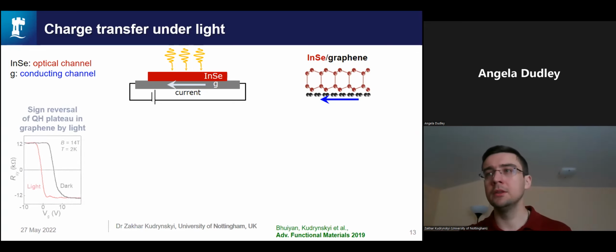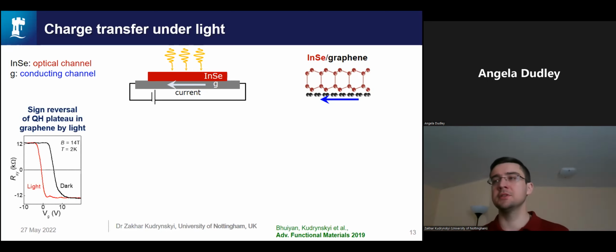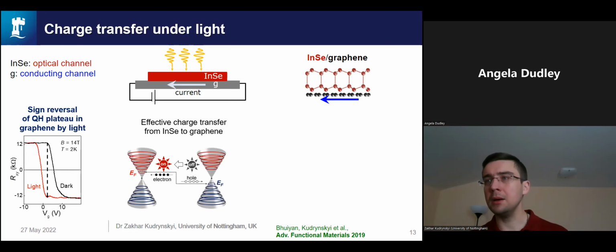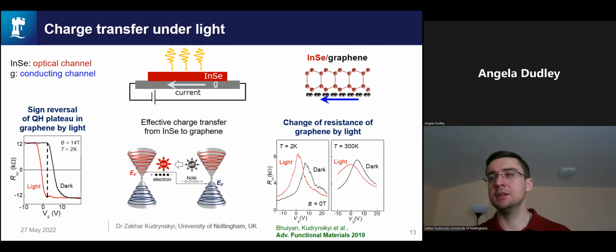So we can look at the Hall resistance versus gate, but also in the dark and under illumination. And you can see that under light illumination, we can change the sign of the Hall resistance. By light illumination, we can effectively change the electron density in the graphene, going from hole type of conductivity to electron type of conductivity. So this also changes the resistance. We can see that the change in resistance under light is not affected much by temperature. It persists both at low and room temperatures.